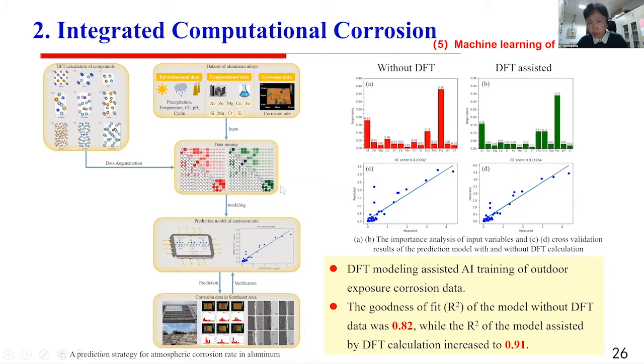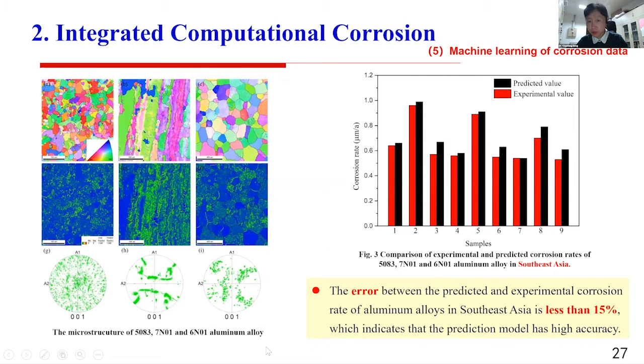Because I can get a lot of exposure data, but the accuracy is not good enough to meet the requirements of other users. So that's why we put in the DFT calculation of the compounds. For example, the aluminum alloys, there are maybe 2000, 5000, 6000 and 7000 series. So we can use the calculation as the input and get very good results. The error between the predicted and the experimental corrosion rate of the aluminum alloy in Southeast Asia is less than 15%. So that can be used.